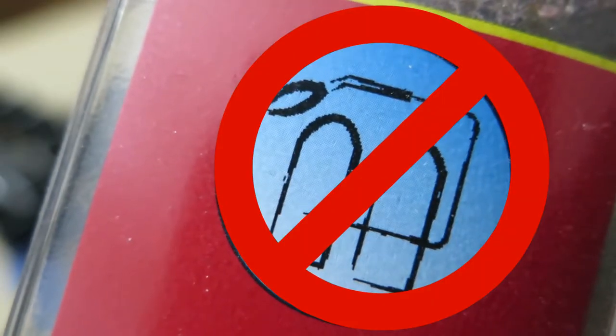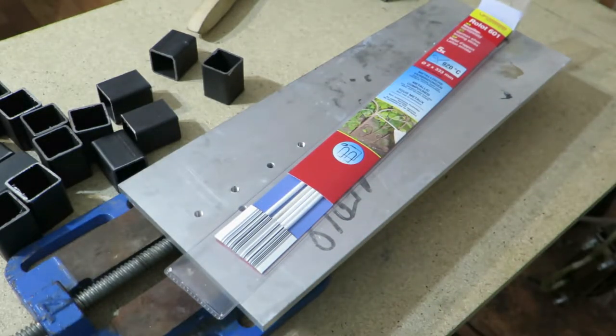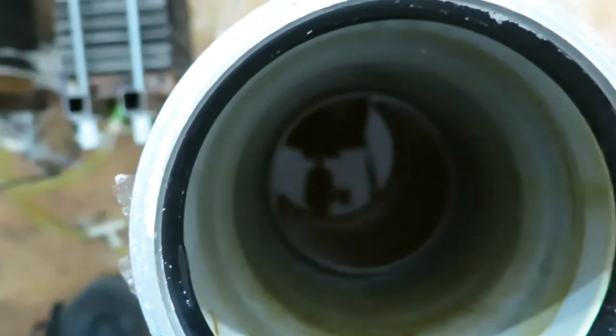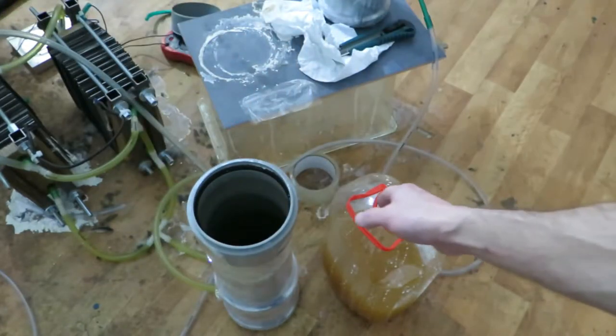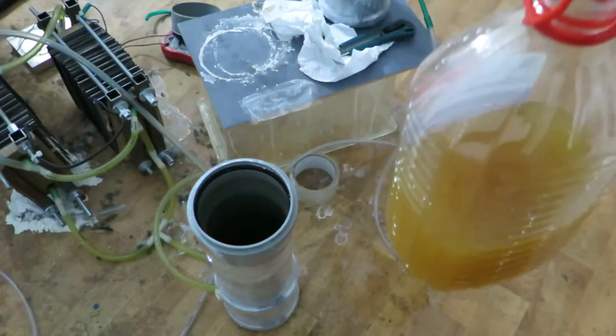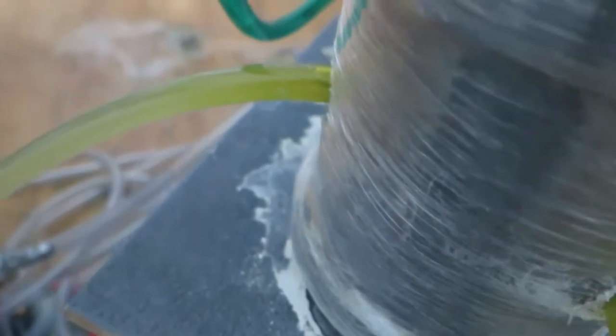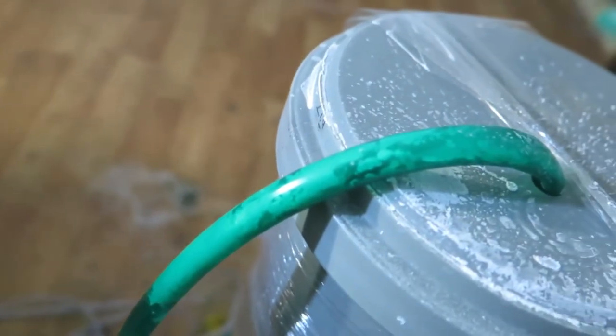Okay, so let's start our generator. It's running at 500 watts, that's no good. Well, it's true that somehow I got my electrolyte contaminated with something. I guess I will have to change it. As you can see, it's brown. Right now I don't know why. I was experimenting with ethanol in a bubbler and it may have somehow contaminated the electrolyte. But the only thing I can do is save a sample and change it. One thing is for sure, either it's from PVC tubes, maybe dissolved plasticizer or pigment, or it's from rubber separators which are EPDM and should be resistant to hydroxides. Also here's some strange material in the holes.